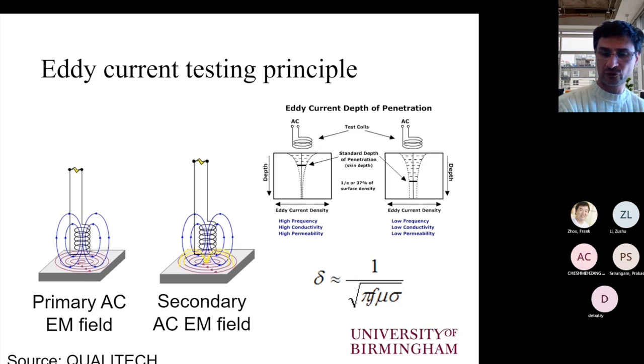In the case of a ferrous material, the relative magnetic permeability will have a value which is different to one. And that means that it will also play a role to the depth that we are inspecting with eddy-current testing. So the higher the relative permeability, the lower the depth of the inspection. Generally, when we are inspecting ferrous materials, the inspection has a much lower depth in comparison with non-ferrous materials because of the very large effect that the relative permeability has on the depth of the penetration.